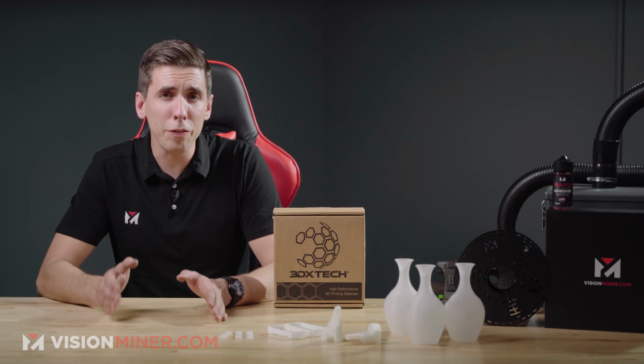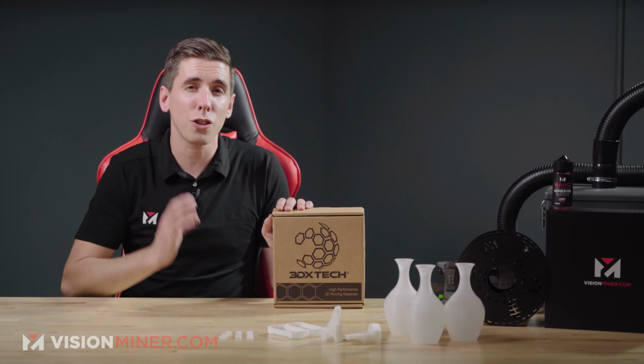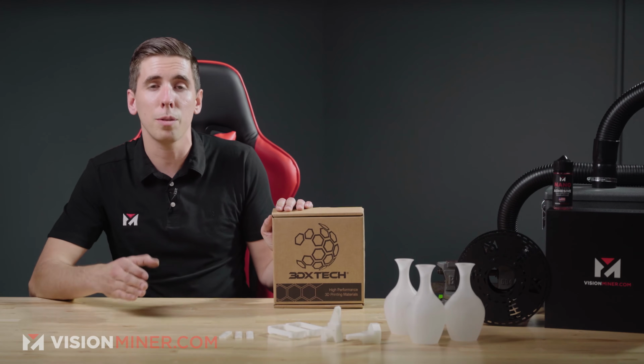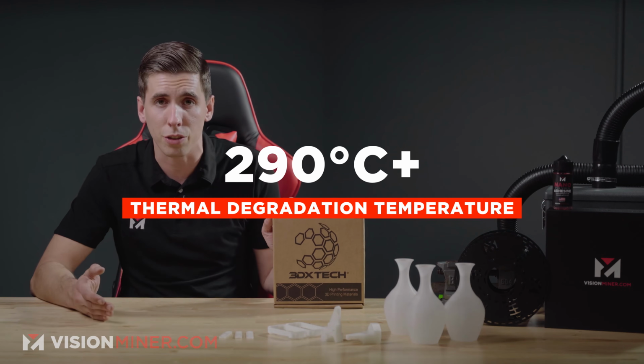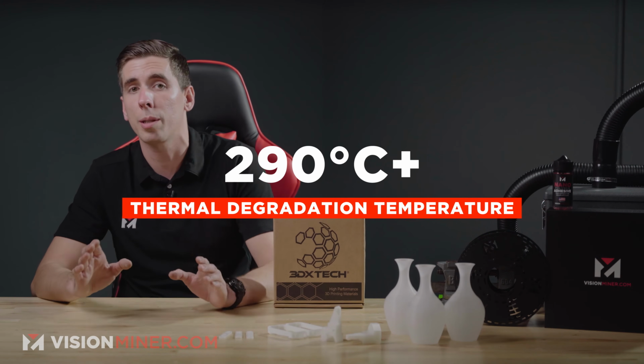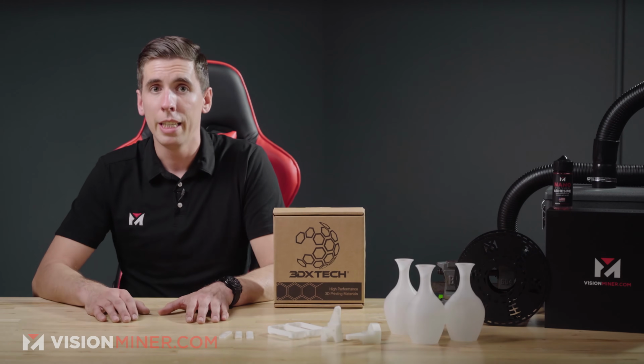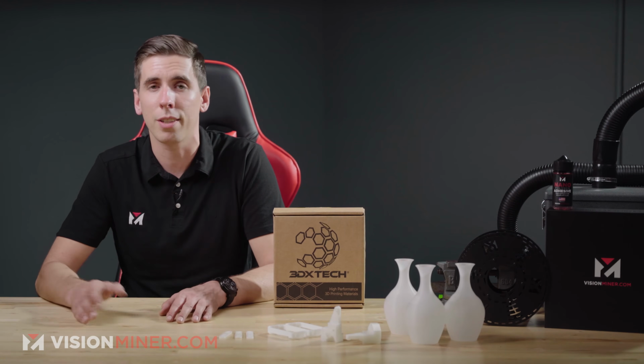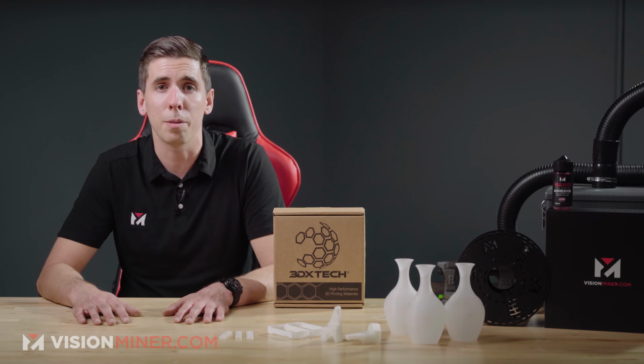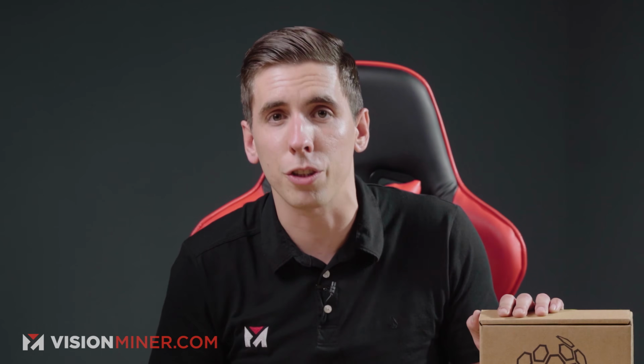Now, as a safety note, this polymer does start to degrade at temperatures above 290 Celsius. So make sure that you keep your extruder temperature below 290 in order to avoid that degradation, the off-gassing, the fumes, and the mechanical property loss is definitely not something you want. So keep it below 290, but you've got a wide range, you can do a lot.